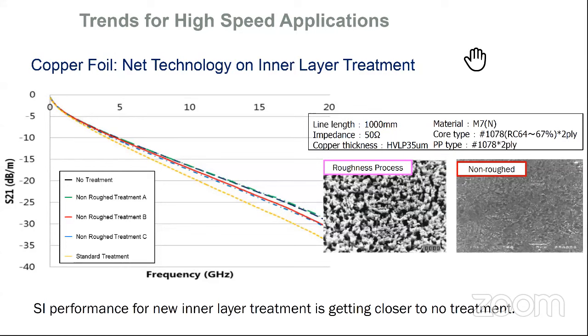The point here is that this development with the chemical suppliers is getting us to a point where signal integrity is getting closer and closer to no treatment. But again, we have to be cognizant of the fact that with this lower profile and lower loss surface, we have to have a special attention on what are we doing for peel strength, bond strength, mechanical integrity, thermal integrity of the total package in the z-axis through reflow or other thermal excursion.